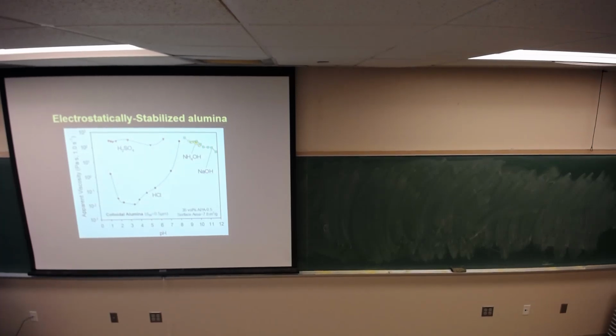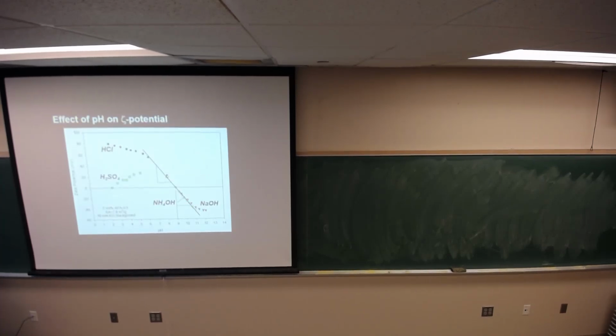Wait, let's look at the zeta potential data. Zeta potential data, well, it doesn't show that to happen, does it? It shows that mine, if I get down to pH 2, I'm at pH 2, so you'd argue it didn't quite show it here, but I'm not seeing a decrease in zeta potential data when I go to lower and lower pHs. And again, it's the same argument, right?